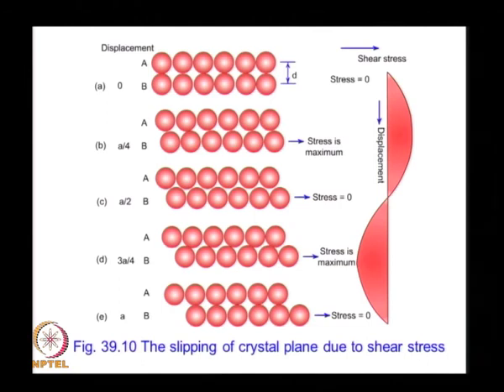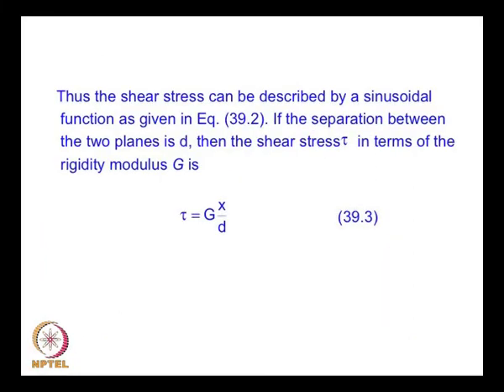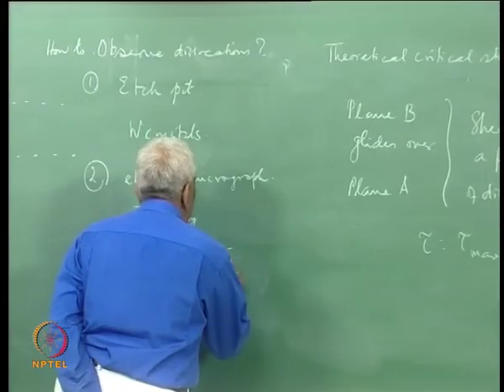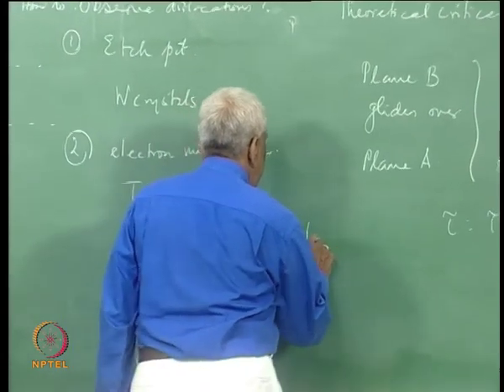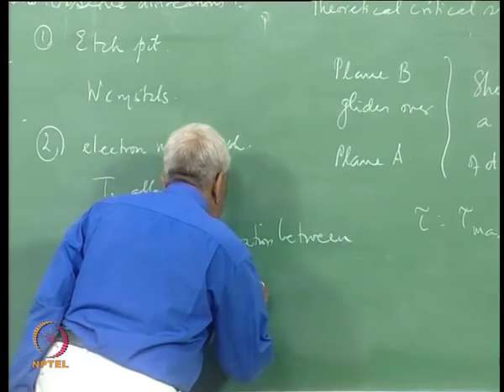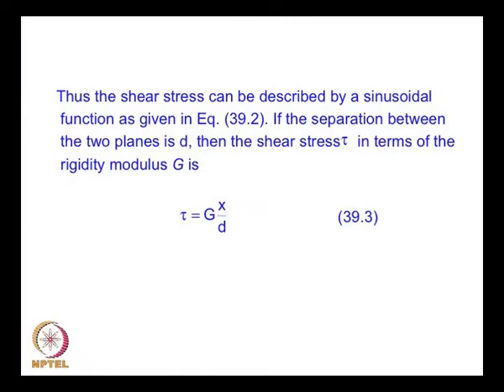This can be seen in figure 39.10, where the slip shows that the stress is 0 at position A, while the stress is a maximum when there is a displacement of a by 4 as shown in B. Then the stress is again 0 for C, where the displacement is a by 2, and again goes to a maximum in the section D, which corresponds to a displacement of 3a by 4. Then again the stress becomes 0 when it becomes a. So, there is an oscillatory kind of variation of the shear stress, and if the separation between the two planes is d, then we can calculate the shear stress using the shear modulus.